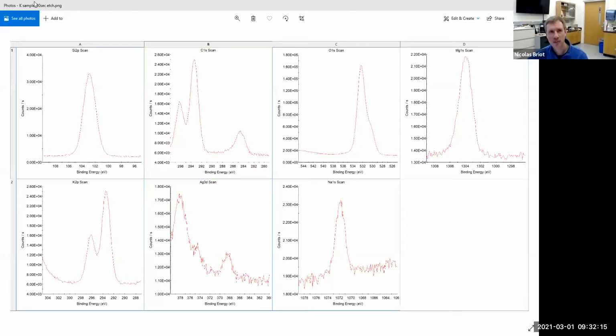Sorry, let me make sure I'm sharing that. There we go. So same sample after etching it 30 seconds. It doesn't tell me a depth, it's kind of moving the beam on it. If you want to know exactly how much you remove, you would have to put some standards, run them, and then look at how deep you go. It takes a little while, and it's part of a big study. But when you just want a quick answer, you don't really have time to do that. What I can tell you is that 30 seconds in our machine, you're not removing microns. I'm talking about removing 10, 30, 50 nanometers maybe.